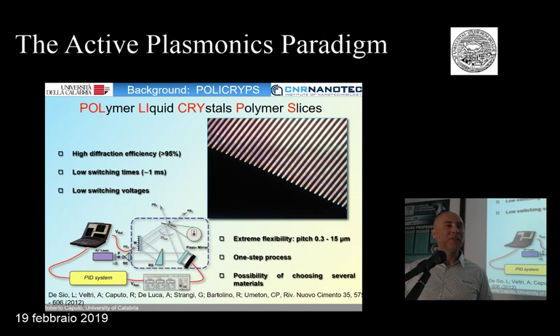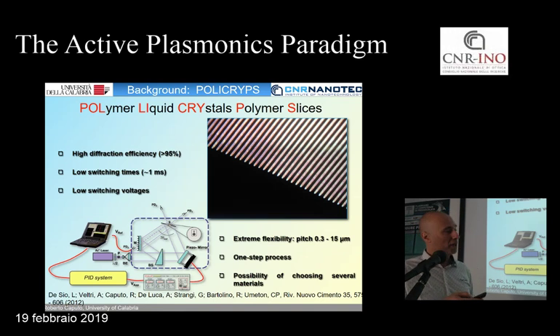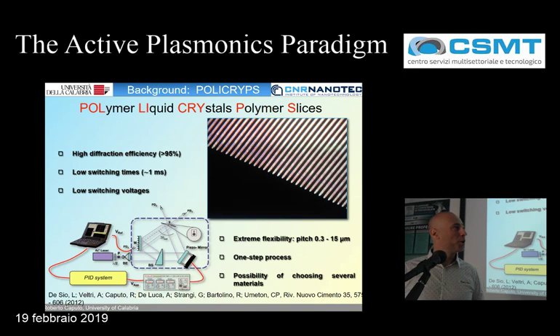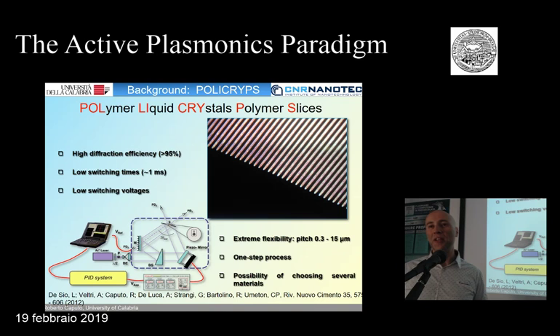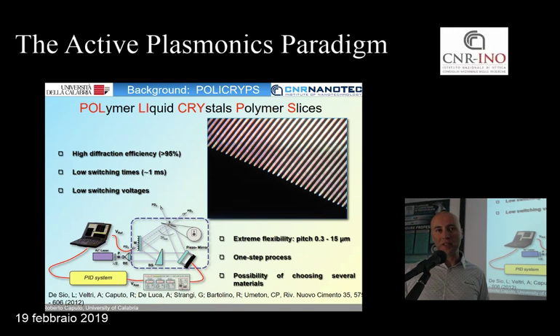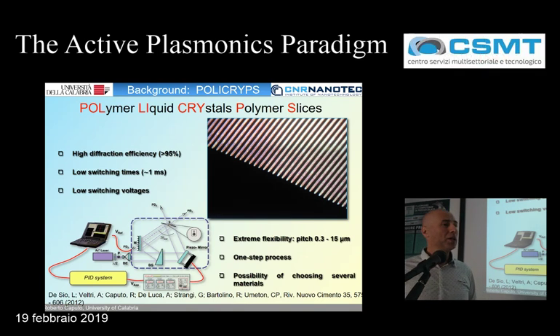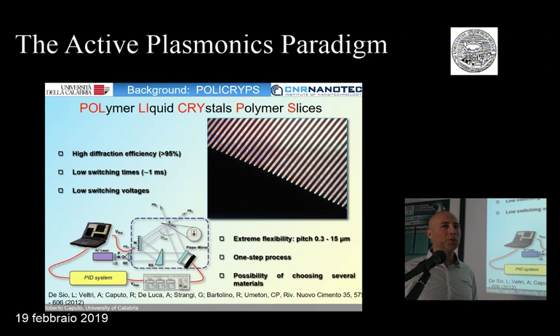So this very nice structure, which is on the microscale, is essentially a diffraction grating, which contains liquid crystals. This system has been studied by our group in the last 15 years, and the nice property of this system is that you can control the diffraction efficiency, if you consider this system as a diffraction grating, by applying an external electrical field, because you can reorient the liquid crystal contained in these very nice channels. This picture is between cross polarizers, so this is the reason why you can see just the liquid crystal within the structure.